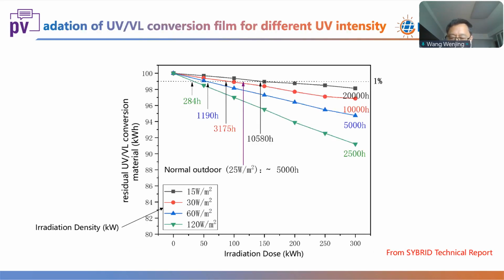There's a report about this kind of UV to visual conversion material. If you use different irradiation densities and exposure times, we can see that with a higher irradiation density, this material degrades faster with the irradiation dose. If the irradiation density becomes lower, it is quite stable. For the outdoor, the density of UV light is just 25 watts per meter square, so it's somewhere like here. For the outdoor, this kind of material is quite stable.